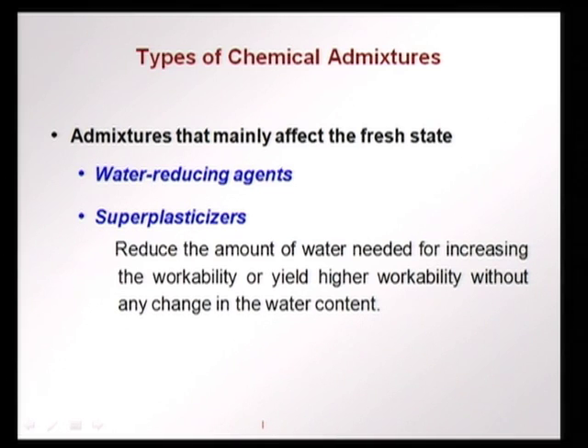Chemical admixtures can be put into different classes. First is the class of admixtures that affect the fresh state of the concrete. These are basically two types: water reducing agents and superplasticizers. Both of these reduce the amount of water needed for increasing workability. That is, when you have an application, when you have a very congested reinforcement or slender element that would need a lot of vibration, which is not possible, we need higher workability and we do not want to increase the water content. If we increase the water content, we will have lower strength and lower durability, which we do not want. Then we go to a water reducing agent or a superplasticizer and we get better workability.